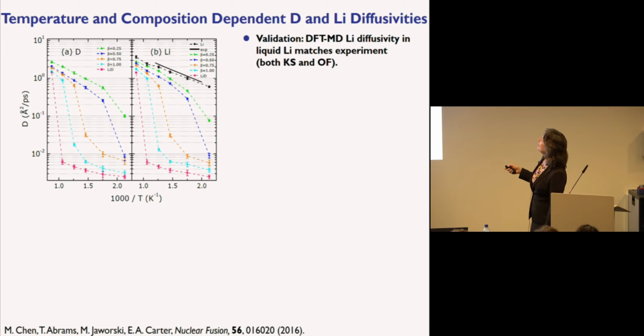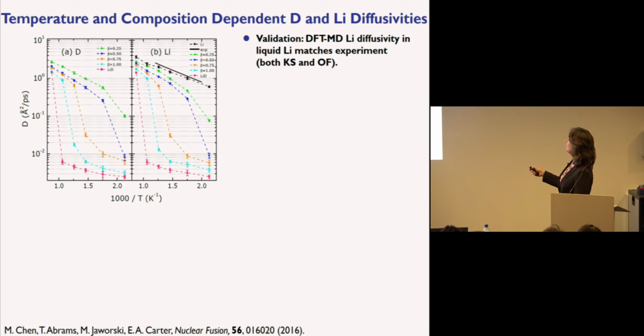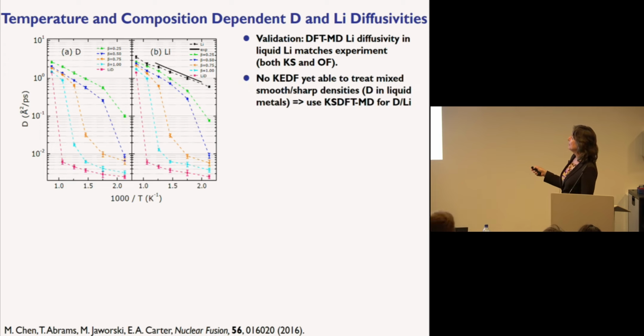And so what you're seeing here is, as a function of adding deuterium, with the pink being already pure lithium deuteride, these discontinuities in the diffusivity as you cool down, and the reason that's happening is essentially you're getting solidification, okay, and you're getting chemical bonding in particular. So I mentioned this point already, that there's no kinetic energy density functional that can treat both smooth and sharp densities, and so all of this is generated with Kohn-Sham Born-Oppenheimer molecular dynamics.